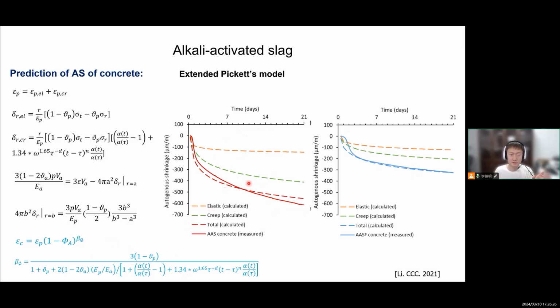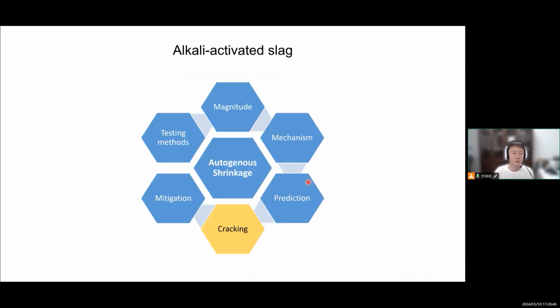But the result is actually very nice, except for the very early age when the reaction is very fast and very complicated. We cannot really predict everything. But after the first days, they really match well with each other. So it shows that the methodology we used should be reasonable, should be fine.